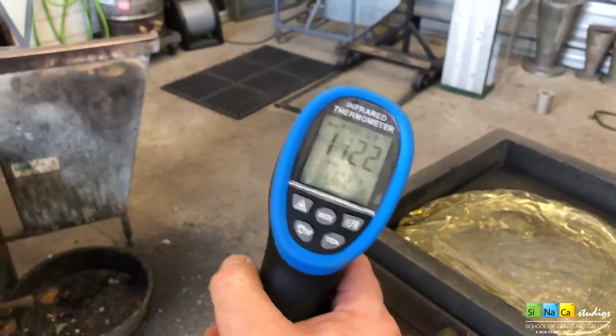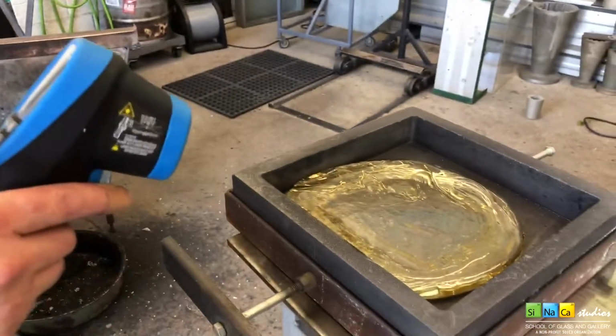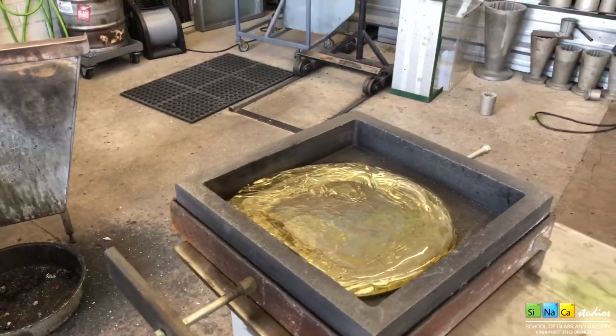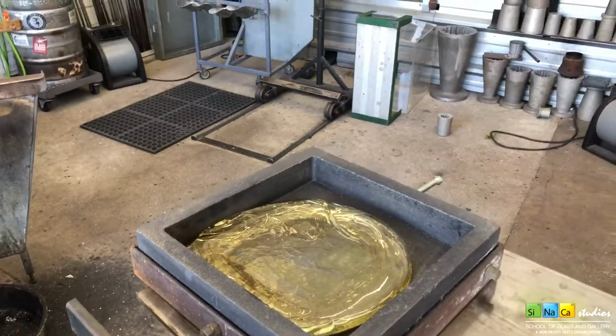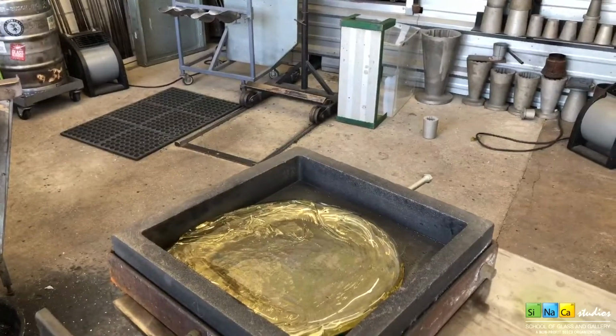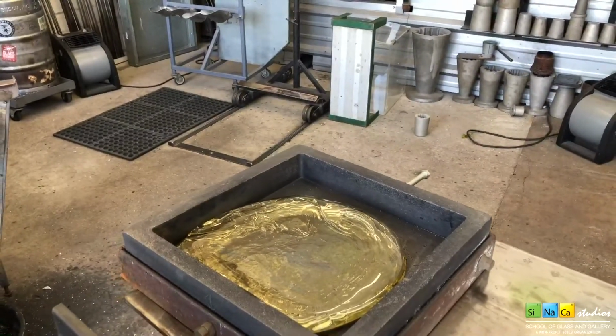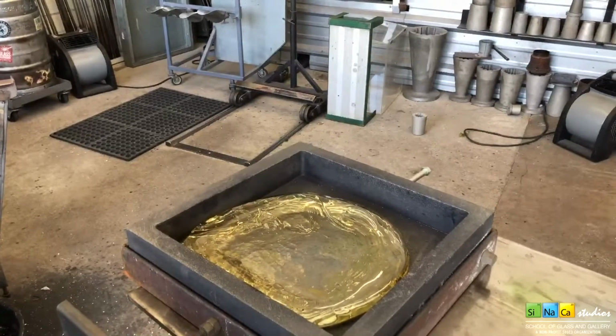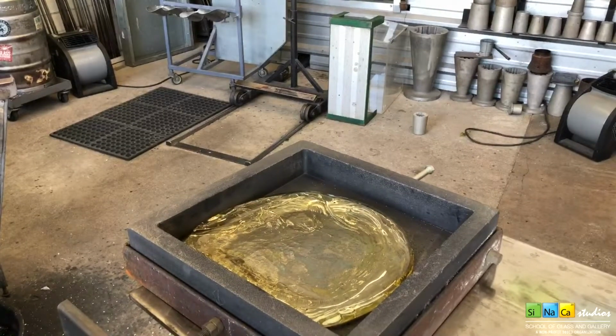1122. Still a little hot for cooking on, but as this glass gets under 1,000 degrees, we are dealing with the potential for the glass to crack. There's a range where the glass really starts to experience stress. So we gotta watch out for that temperature zone, but we also can't cook eggs on over 1,000 degrees. So the team is gonna let it cool down a little bit before throwing eggs and bacon into it.